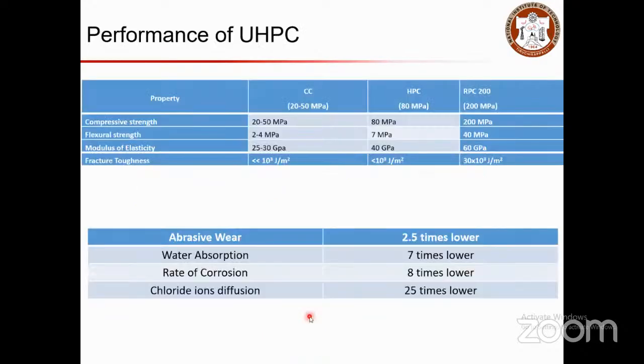So let us compare the performance of the ultra high performance concrete here. So it's conventional concrete, high performance, and ultra high performance concrete. The strength would be for the conventional concrete in the range of 20 to 50, and for high performance concrete it is about 80, and for this ultra high performance concrete, this is reactive powder concrete that is mentioned, it's about 200 MPa also. And flexural strength it is 2 to 4, and here it is 7, and ultra high performance concrete is about 10 times the conventional strength that we have, and modulus of elasticity in the range of 30 for conventional, 40 for high, and about 60, twice the conventional strength for the ultra high performance concrete.